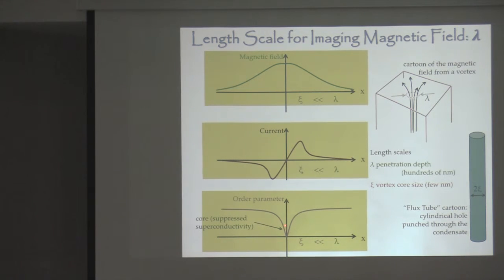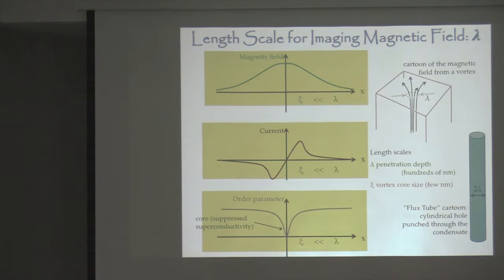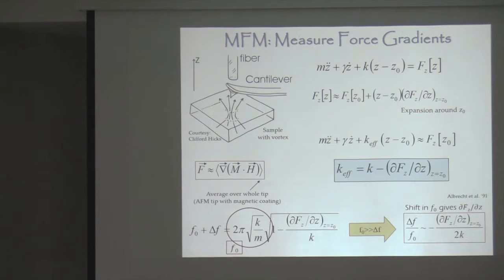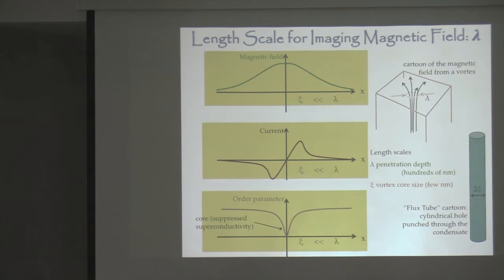That doesn't mean that we can't see things that happen on a really small scale, because if you see something moving, and you have a good signal to noise, you can be sensitive to things that are even on the scale of the coherence length. And the coherence length is important because that's what's going to determine, for example, when we do vortex imaging, where vortices sit. The reason they sit somewhere is that the core likes to sit somewhere. So that's the scale.